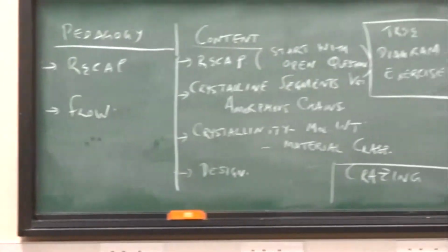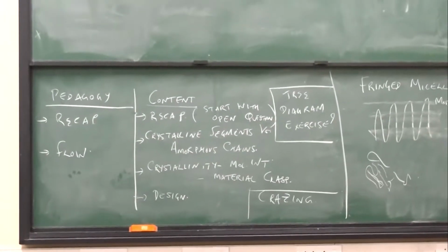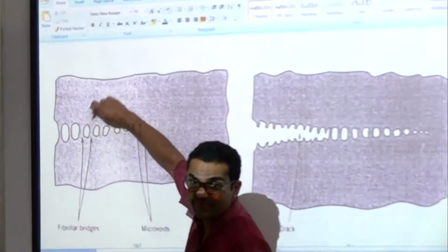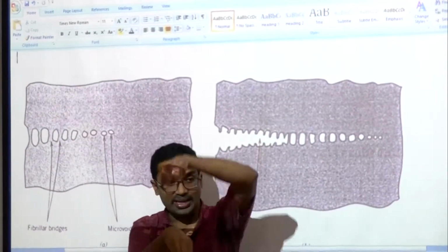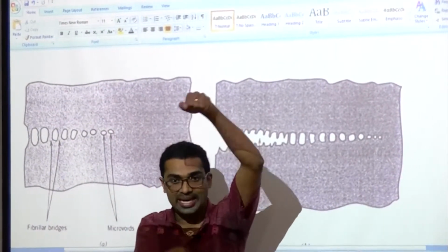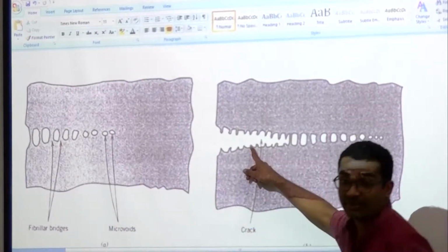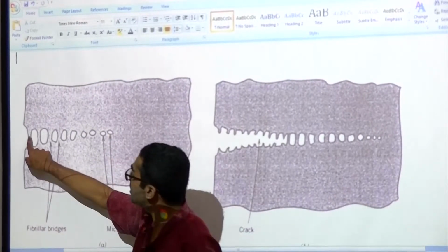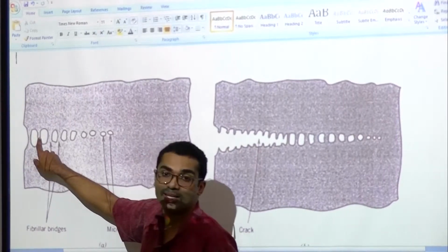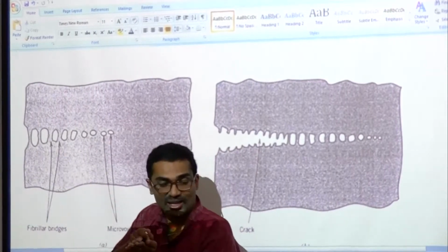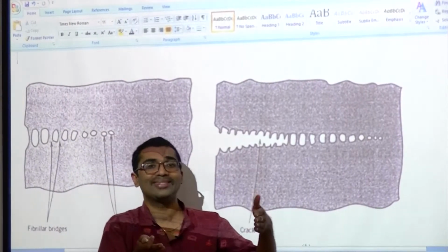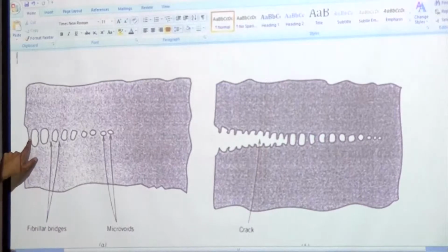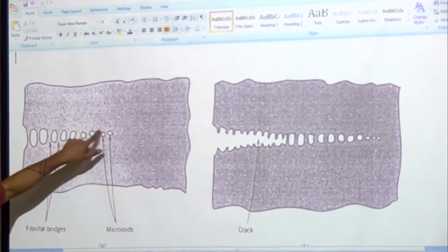So you have these bridges here, okay, so these are called fibrillar bridges. You have a lot of stress and that results in alignment here, okay. There is progressively higher and higher amount of alignment here. So, but there is bridging, there is no discontinuity yet until discontinuity sets in. When does discontinuity set in? When this snaps. Typically this will snap before this does, and this will snap before this does. So there is a propagation of this. This is somewhat analogous to crack propagation in a polymer. Okay, this region opens up, then this opens up, and so on.